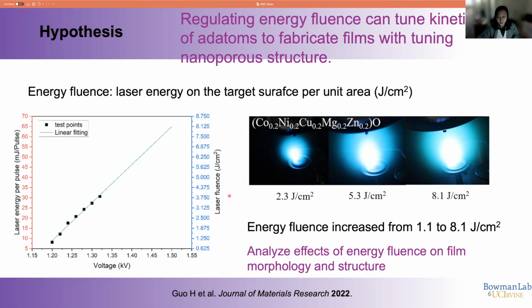They also will let more material leave from the surface of the target to the surface of the substrate. They also increase the deposition rate. So in our PLD machine, we use the voltage to control the laser pulse energy and the laser fluence. They have almost a linear relation. It's very convenient for us to control the voltage to control the laser fluence. In this work, the energy fluence increased from 1.1 joule per centimeter squared to 8.1 joule per centimeter squared. Then I will analyze the effects of energy fluence on the film morphology and structure.